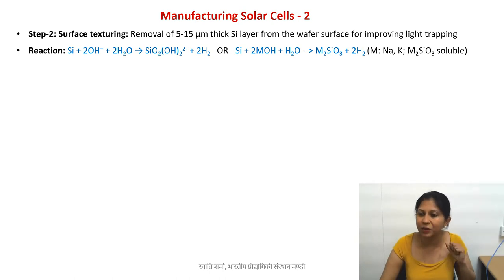In the first reaction, silicon oxide is formed consuming some silicon. In the second reaction, metal silicon trioxide is formed, also consuming silicon. This compound is silicate which is soluble in water, so it goes away with the aqueous solution and we get etched silicon.